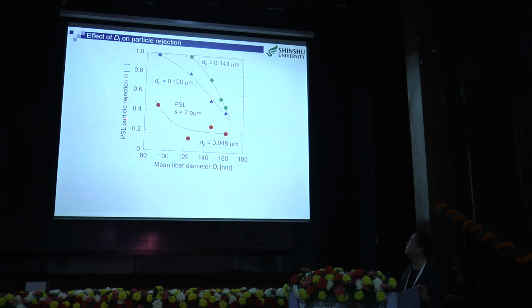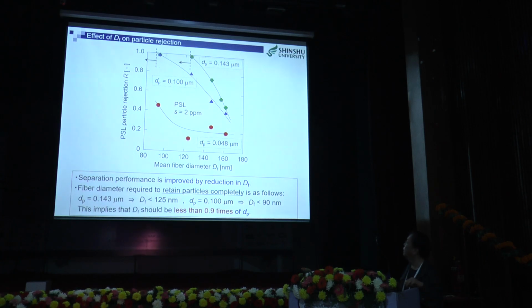This figure shows the PSL particle rejection R against mean fiber diameter. As shown in this figure, the separation performance is improved by reduction in fiber diameter. Please note this part. Fiber diameter required to retain 0.143 micrometer particles completely is about 125 nanometers. For 0.1 micrometer particles, fiber diameter required to retain completely is about 90 nanometers.